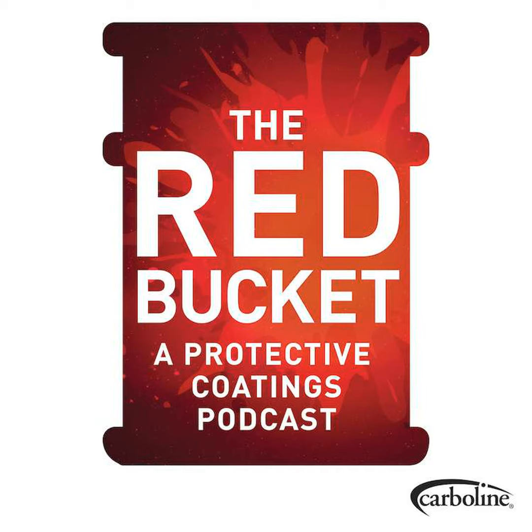It's quite corrosive actually, and there's a couple different mechanisms for that even, but the main thing is the elemental sulfur can react with the carbon steel and form basically iron sulfide layers, and that iron sulfide layer can actually passivate that substrate a little bit, but it can also be weakened and be part of the overall corrosion process. It's kind of a catalyst in the whole corrosion process, not to mention the fact of the molten aspect of the sulfur, the heat that's involved, and the flowing that's involved. The heat alone is quite damaging to lining. So that combined with the corrosive nature of the sulfur itself creates a pretty bad environment for a lining